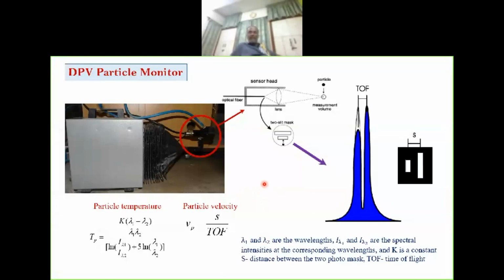For velocity measurement, we have to track a particle for a small distance, plot the time, with the distance known, and we can get the average velocity before impact over a short distance, which is close to the real instantaneous velocity. Kindly note, dealing with these instruments is not always easy, but it's possible.